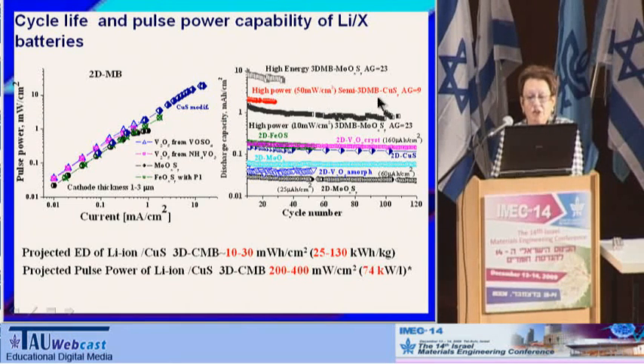The capacity of semi-three-dimensional microbattery with modified copper sulfide varies from 1 to 2.5 milliampere hours per square centimeter. This is in good agreement with the thickness of the cathode, with its composition and morphology, and also with the area gain. In the case of semi-three-dimensional microbattery on silicon, the area gain was relatively low and equal only to 9. This cathode in the semi-three-dimensional configuration delivered something about 60 milliampere per square